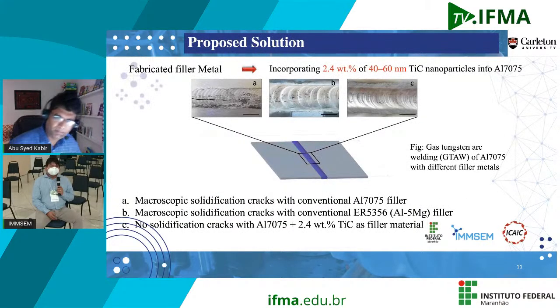Now, this is what they published. Okay, so they welded 3 different aluminum 7075 sheet metals, one with conventional 7075 filler metal, so the base metal and filler metal are the same. They used aluminum 5% magnesium filler metal, which is a very conventional filler metal generally used to weld 7075. And in the third way, they used aluminum 7075 filler metal, but that filler metal was incorporated with 2.4 weight % titanium carbide nanoparticles.